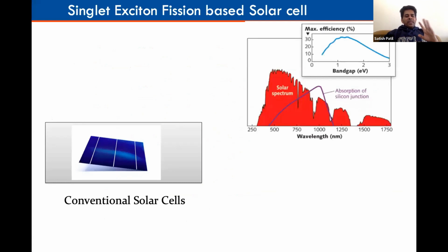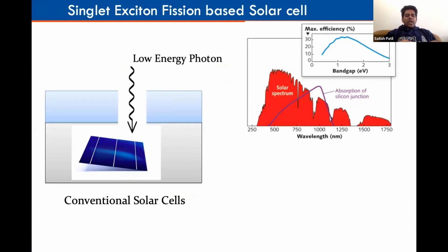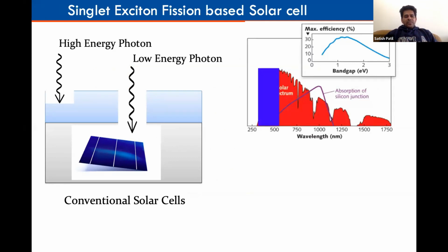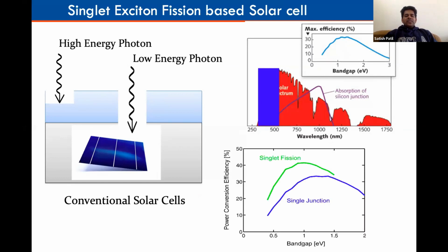Going forward in a similar area, we recently started a concept called singlet exciton fission based solar cells. So let's take a silicon which takes away the low energy photon, and you coat an organic dye upon it. When you coat the organic dye, you don't simply coat it. The dye has a specific property. It takes away the high energy photon, which is not doing the important work in the case of silicon, because those high energy photons you lose in the form of thermal energy. We coat the dye upon it. Essentially, the dye has a property called singlet exciton fission.